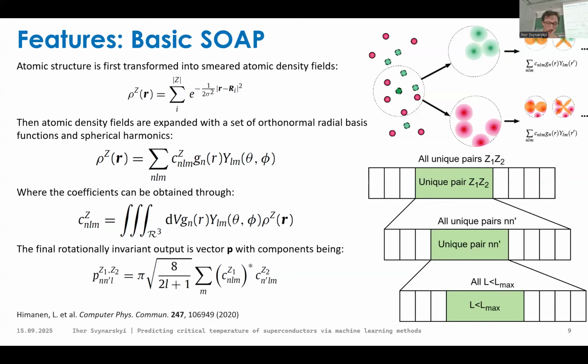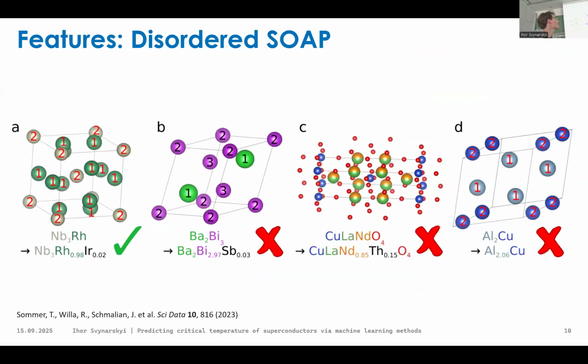And that's why they are using this modification called disordered SOAP. So it basically looks for our ideal structure. Let's say we have this formula, and we are searching for similar enough stoichiometric compounds. And then if we can find two, three, or a few of these compounds, they would calculate the SOAP of them and again, using a weighted average, construct the descriptor for these structures. But sometimes you couldn't find a close enough structure for each present structure.